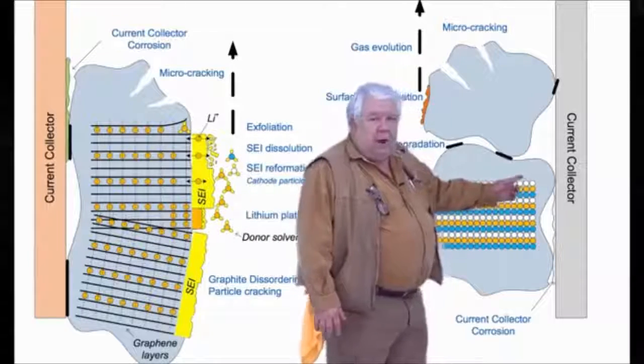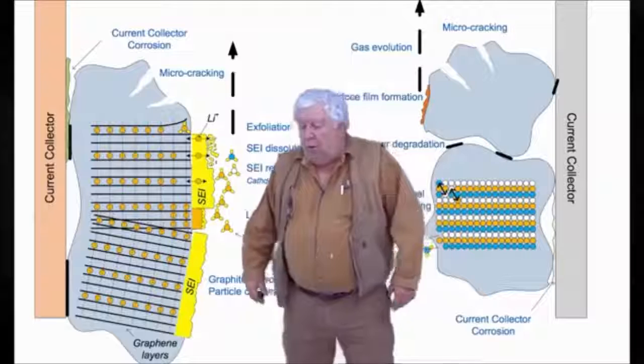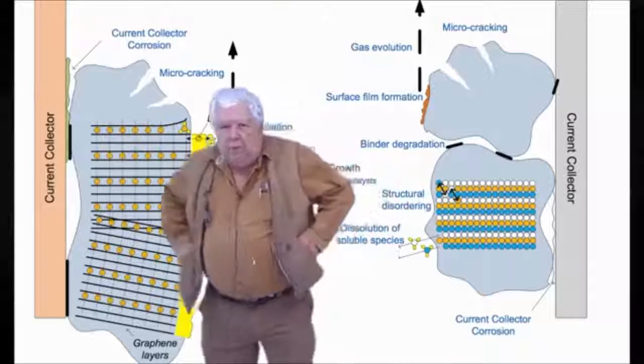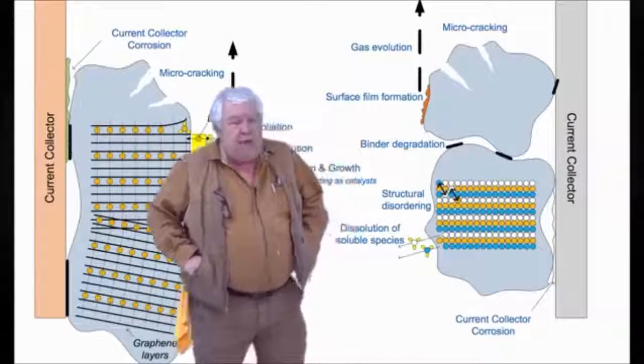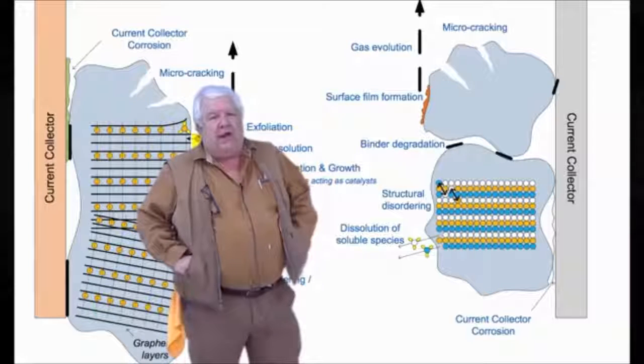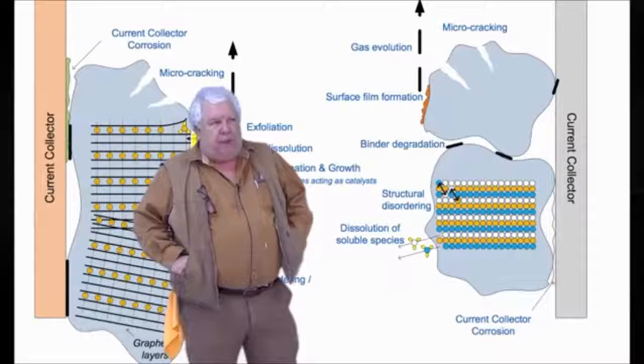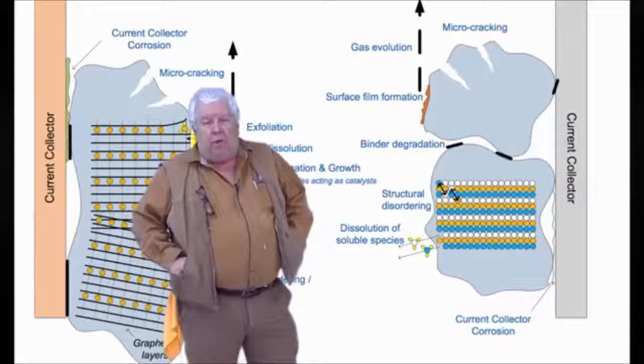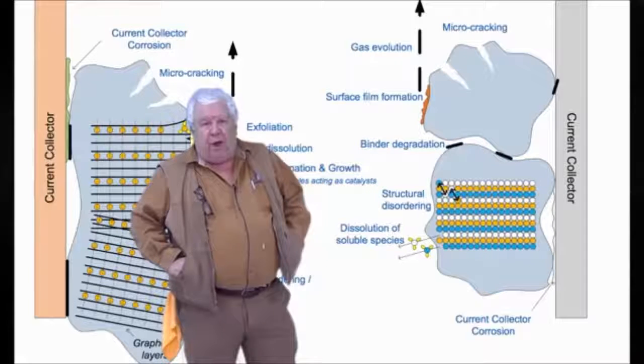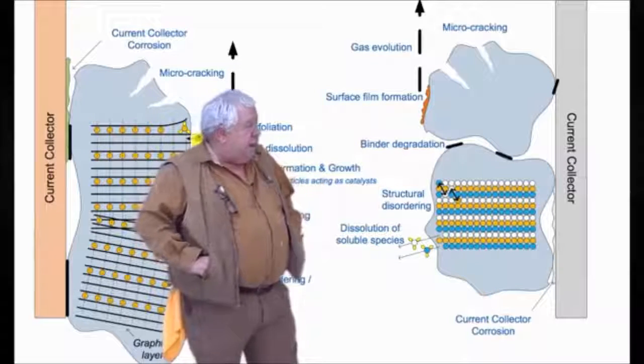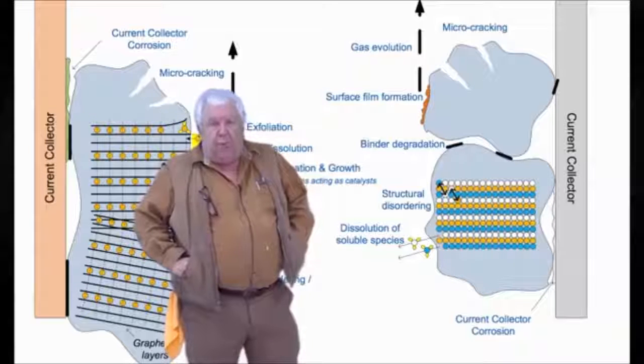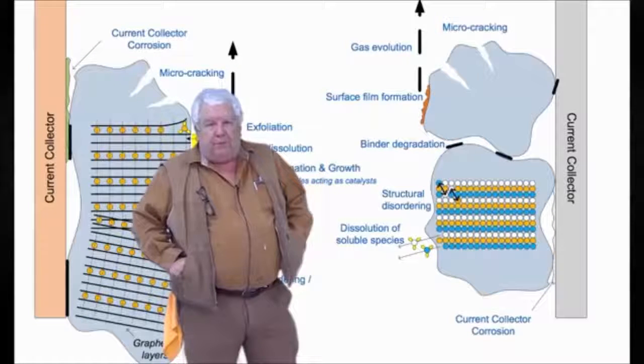It's better to have a lithium iron phosphate cell than a lithium cobalt simply by temperature. But neither one of them will spontaneously and as if by magic burst into flame, no matter how roughly you handle them. External temperatures can bring these up to where all this happens anyway. Above 110 degrees centigrade, the SEI layer is going to start to melt, even if the battery is not working. Above 150 in lithium cobalt, it's going to start giving off free oxygen.